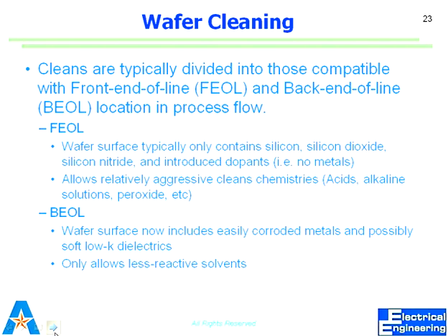Before I go into these much more involved processes, solvent clean is a simple process which gets rid of many, many basic organic materials. I can use solvent clean on wafers as well. It's comparatively delicate, relatively less harsh cleaning. And when I use acids in any type of cleaning, those are harsh treatments. So if I have devices which have very small features, maybe I have some metal deposited which is 10 nanometers wide, I want to stay with solvent clean.